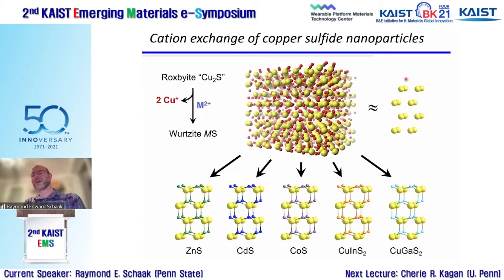And so essentially, this is a distorted HCP array of sulfur anions with Cu+ cations kind of swimming between the close-packed layers. And the copper cations are highly mobile. They can diffuse pretty quickly, think about an ionic conductor. And so it's fairly straightforward to kick out these copper plus cations and replace them with M2+ or M3+ cations. And so here's just five examples that we use quite frequently.